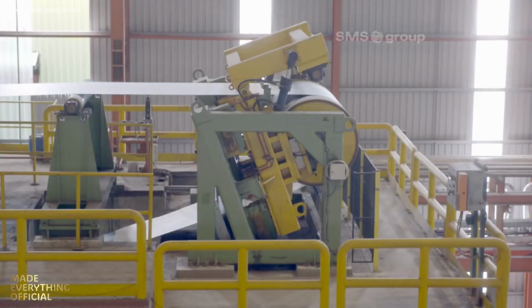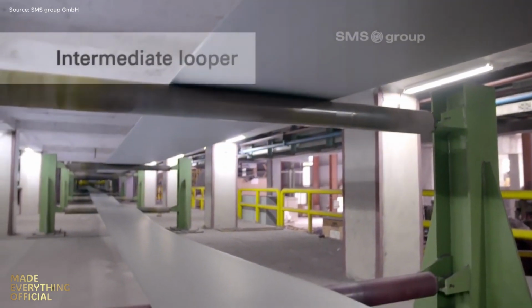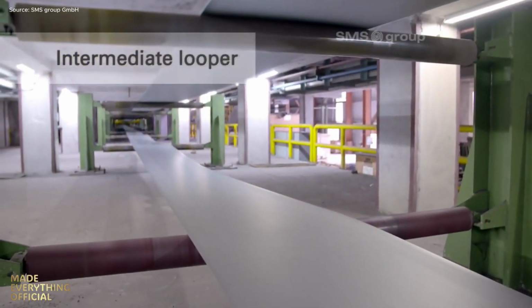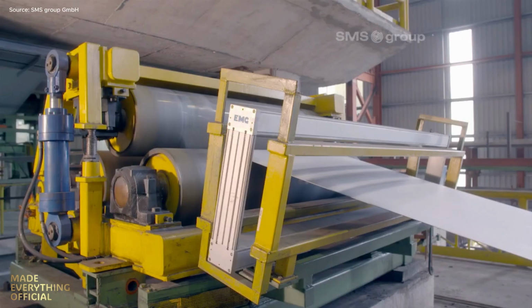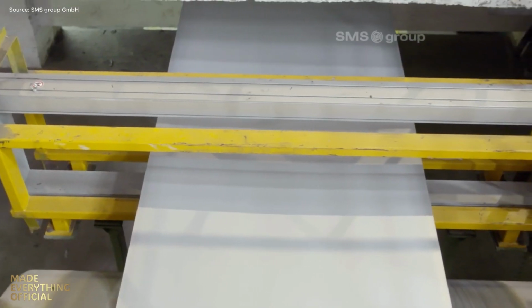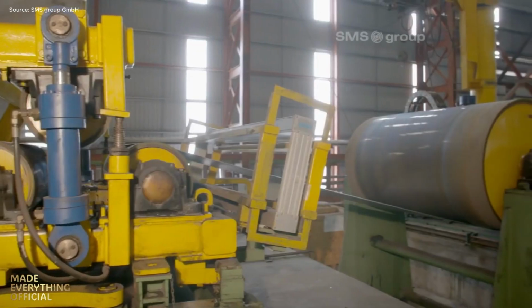The transformation is extreme. Steel entering at 6.5 millimeters can be rolled down to only 0.3 millimeters at a speed of 450 meters per minute. Every parameter is automatically monitored and adjusted in real time for the highest accuracy and surface flatness.